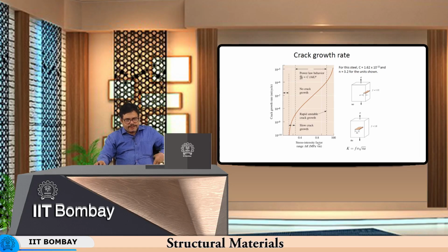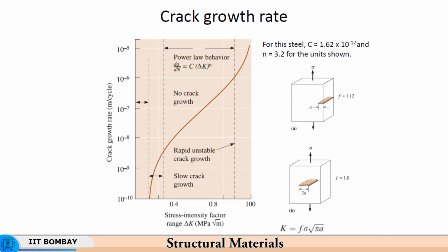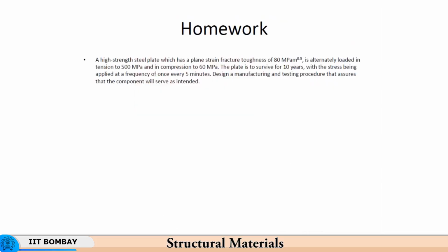As the crack grows more rapidly over here. So, you see there is a slow crack growth here and there is a much more rapid crack growth here. The rate at which delta K will increase, meaning the delta K will shift to the right, continues to increase, and then here it becomes extremely high.